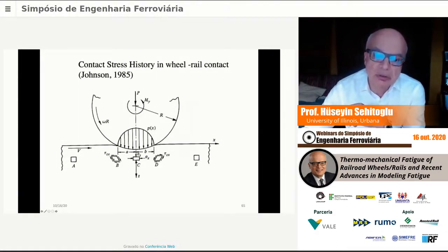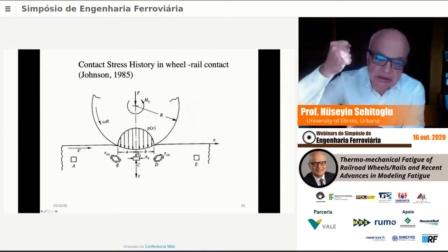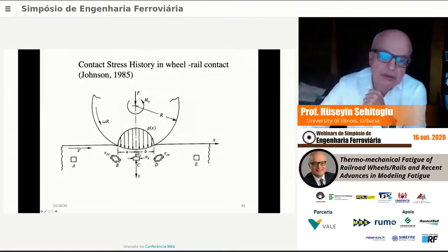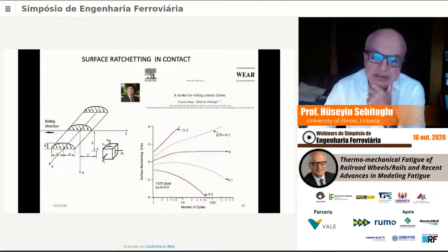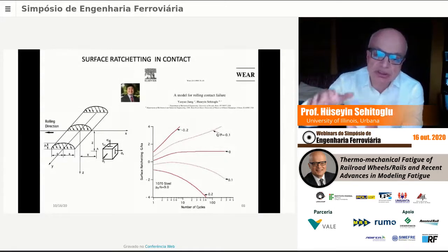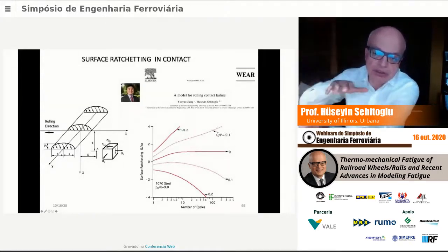And here is your contact patch. He's showing just normal stresses here, of course. It's like a pure rolling case here, but you could have shear tractions. And the thing is this, as away from the contact, you have a shear stress in one direction. And then when the contact is under the point, you get more or less the pummeling, like you have only very high compressive hydrostatic stresses. And then as the contact exits this region, you get shear in the reverse direction. So it's shear, push, and shear in the reverse direction.